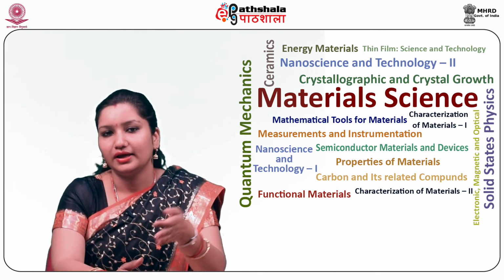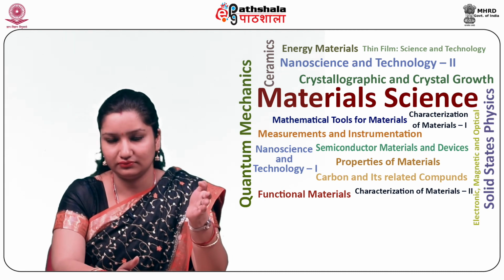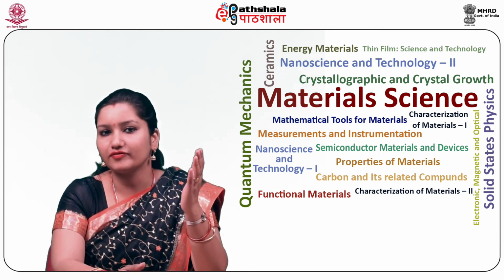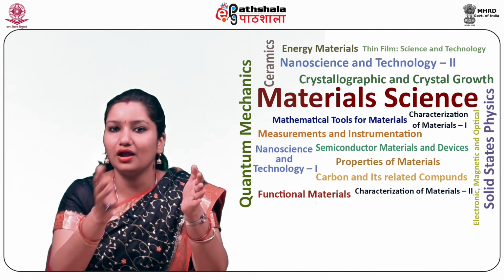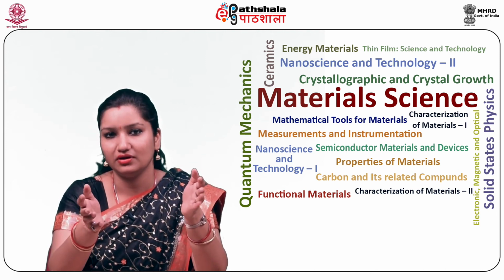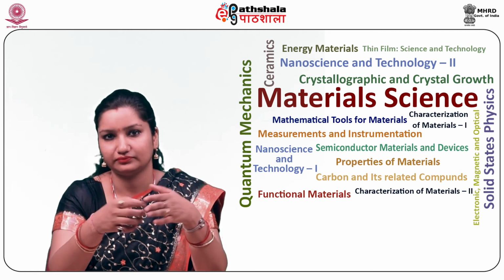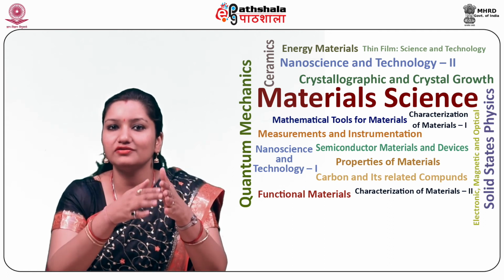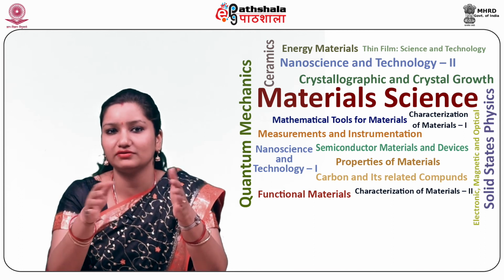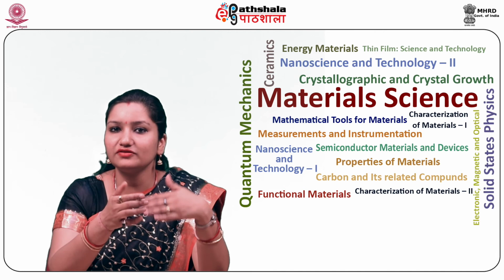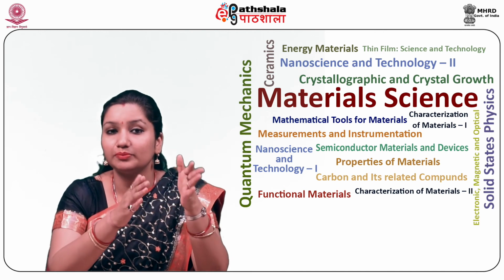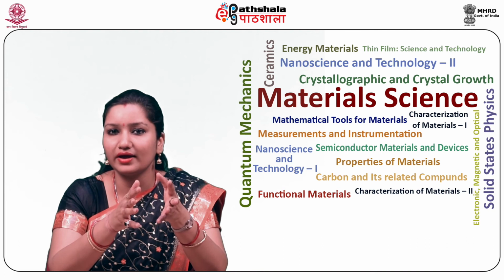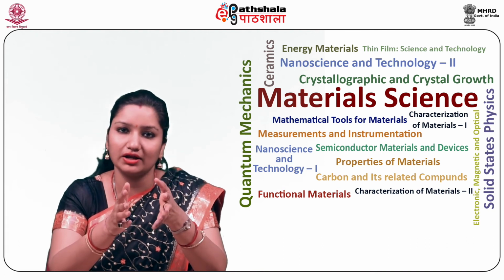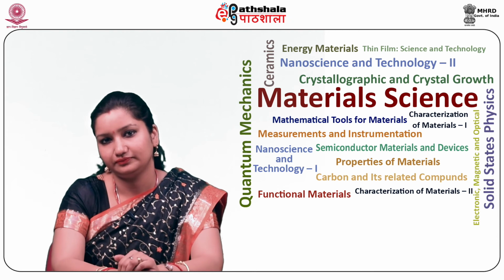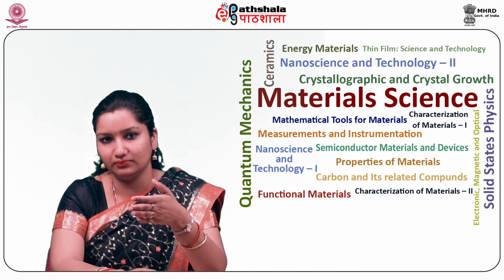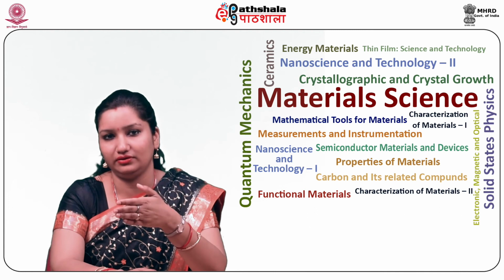In this method, a beam of white radiation, that is X-rays of continuous wavelength, is allowed to fall on a single crystal which is held stationary. The Bragg angle is thus fixed for every set of planes in the crystal, and each set selects and diffracts that particular wavelength which satisfies Bragg's law for the particular values of d and theta. Each diffracted beam thus possesses a different wavelength.